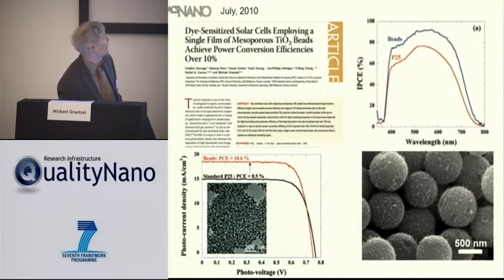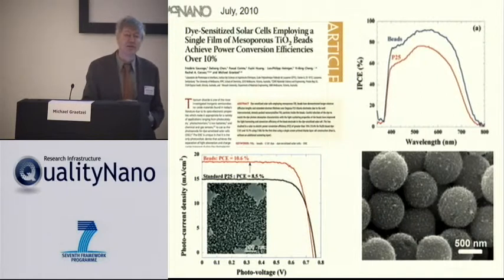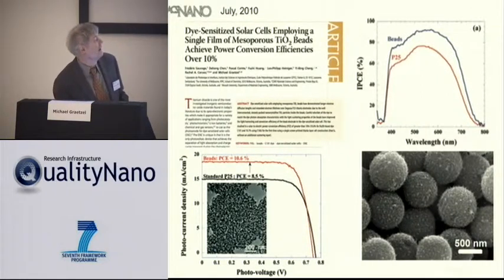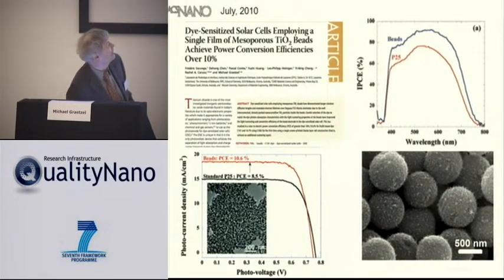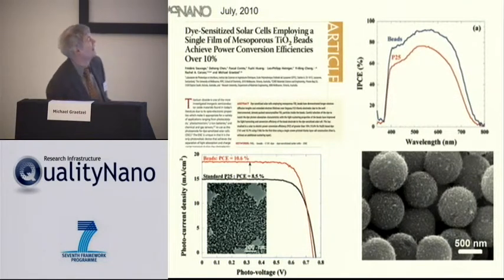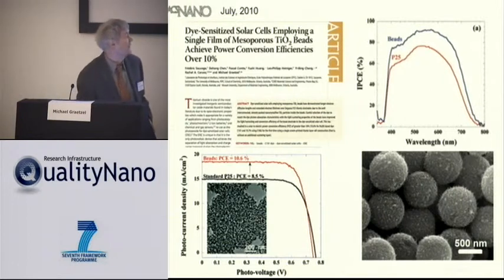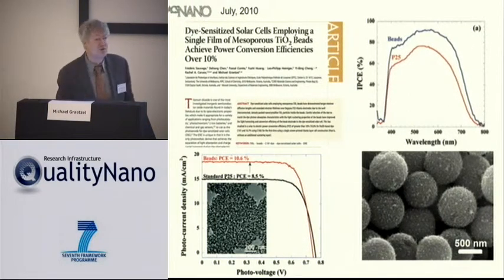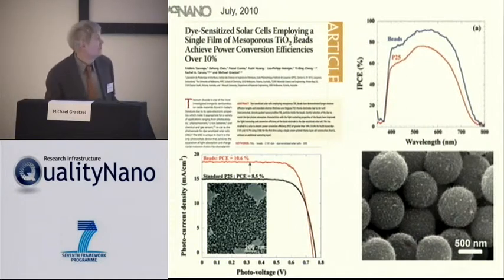They not only have a very high internal surface area, so they can capture the light by light absorption, but they also scatter. And you can see the blue curve has a better response than the red curve. The incident photon to current conversion efficiencies are better with those beads than with normal nanoparticle films. So those beads are very nice, and certainly we have to commend our Australian colleagues, Yibing Cheng and Rachel Caruso, for having developed these beautiful systems.